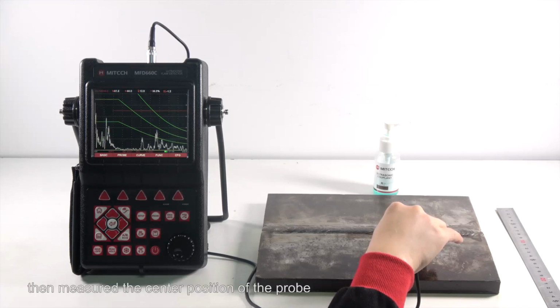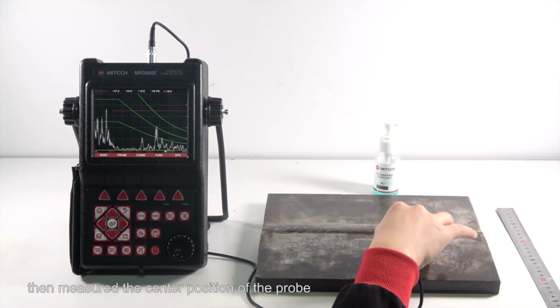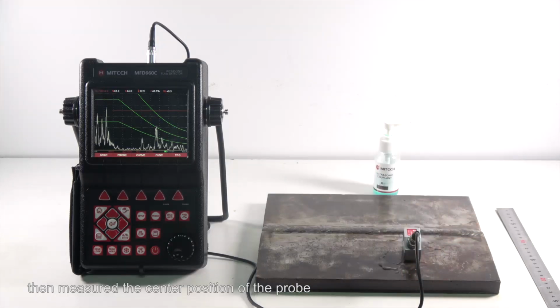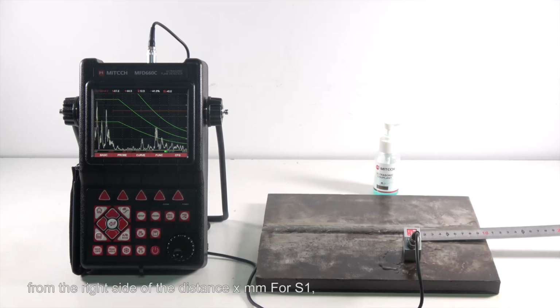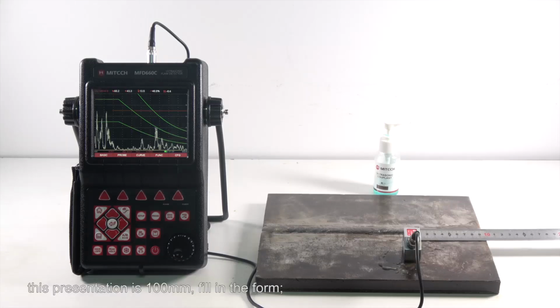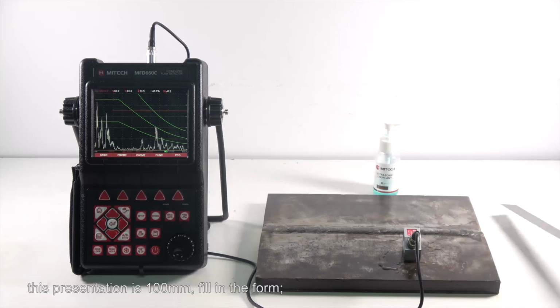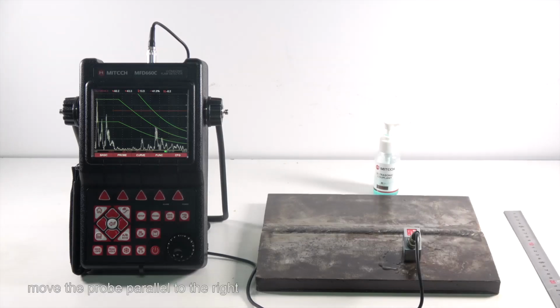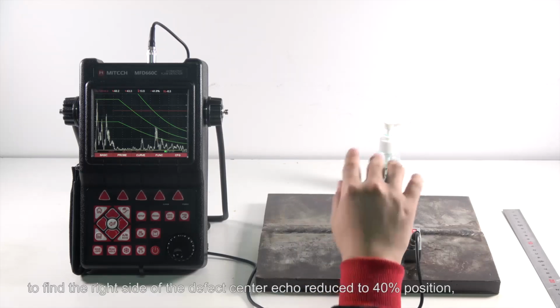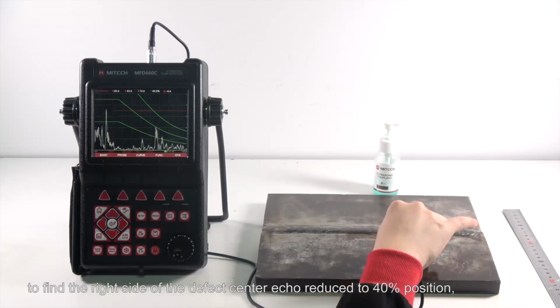Then measure the center position of the probe from the right side, distance X millimeters, as S1. This demonstration is 100 millimeters. Fill in the form. Move the probe parallel to the right to find the position where the right side of the defect center echo reduces to 40%.